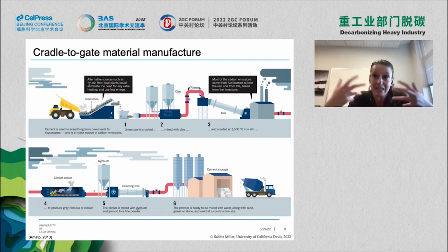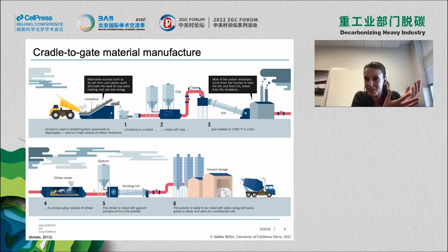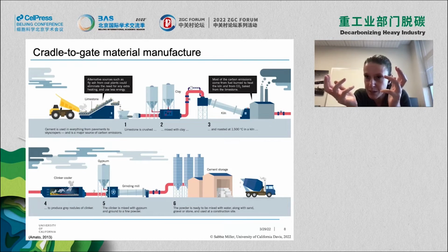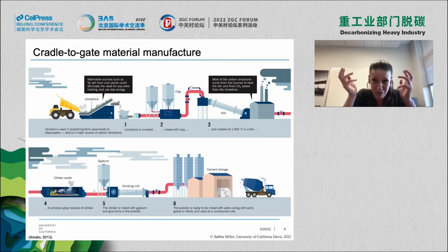When we want to make clinker, which is a solid precursor to our cement, we have to incorporate the silicates. We use amorphous silicates with this lime base in order to form calcium silicates, which then allow us to make this hydrate product at a later stage. And in order to get the calcium silicates to form, we actually need to cook the material at an even higher temperature. While this particular chart calls it out at 1500 degrees Celsius, our more recent kilns, this is a slightly old diagram, are closer to the 1400, 1450 degrees Celsius range in terms of the temperature that's necessary.